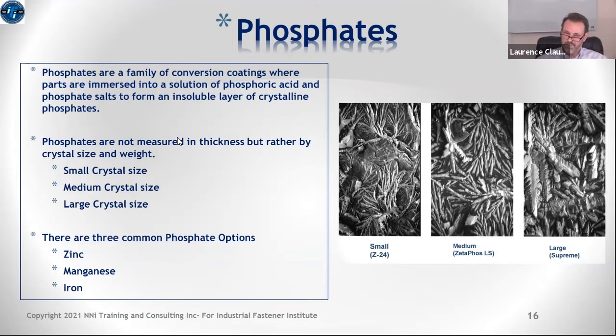When an applicator is validating that they have done this right, they're not measuring thickness, because you can't really measure thickness on this. They're measuring it by crystal size and weight. So what you normally see on a print of a phosphate requirement would be something like grams per centimeter squared, or ounces per inch squared, some kind of measurement of weight over a prescribed surface area. There are three types of common phosphates: zinc, manganese, and iron phosphate. Zinc phosphate is by far the most commonly used on fasteners. Manganese phosphate is a very distant second.